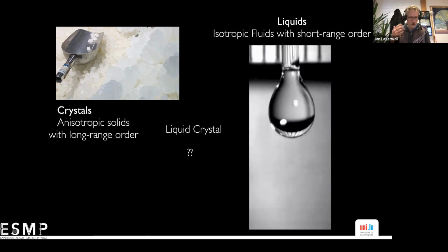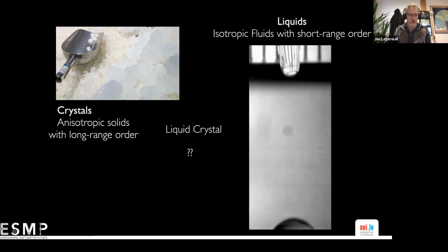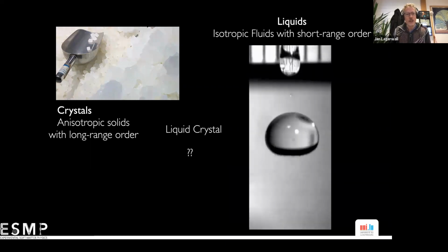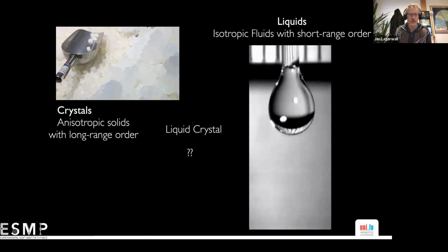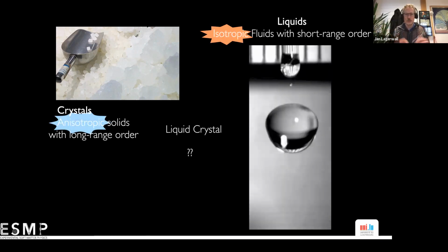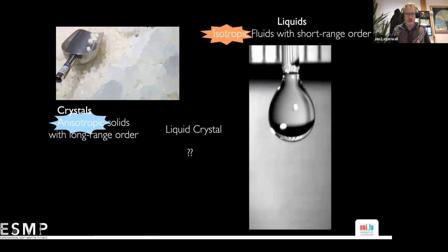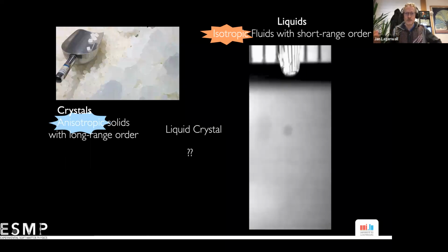They don't have to be anisotropic optical properties. It depends on which tensor you're dealing with, and which the crystal structure is. Cubic crystals are optically isotropic, but the crystals are always anisotropic in higher order tensors. And many non-cubic crystals are also optically anisotropic. So this distinction between isotropic and anisotropic is often how we determine whether something is long-range ordered.